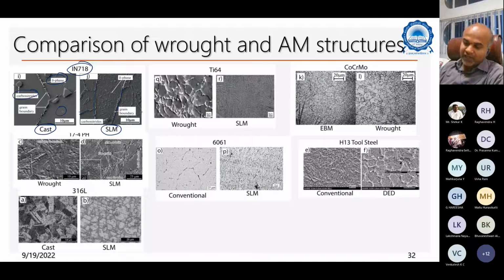And then within the grain, you don't have any delta phases here, whereas in the AM sample the delta phase also appears in the grain, which is good or bad, that once you do the experiments and understand the high temperature properties and creep properties, then only you're able to see. Apparently, what I found is that the 718 SLM sometimes outperforms the conventional as-cast 718, because this delta phase distributed within the grains will also give you certain beneficial properties for 718 material, which is why 718 is very widely used as an additively manufactured alloy. Okay, that is something which is.